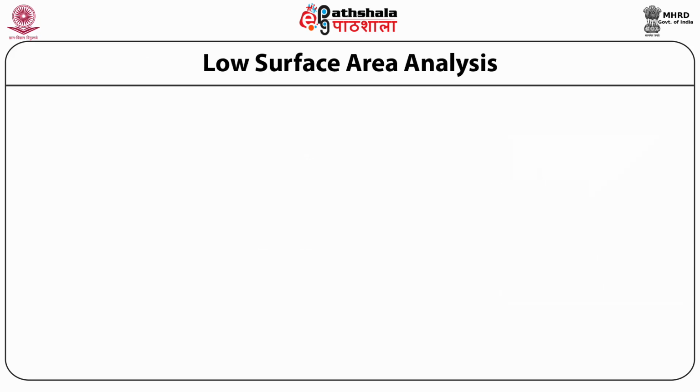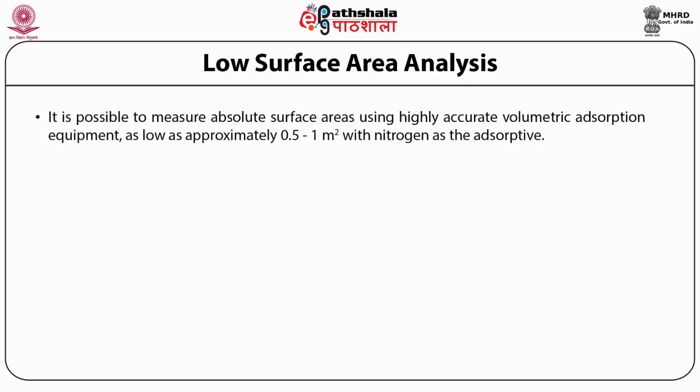Low surface area analysis. It is possible to measure absolute surface areas using highly accurate volumetric adsorption equipment as low as approximately 0.5 to 1 meter square with nitrogen as the adsorptive.